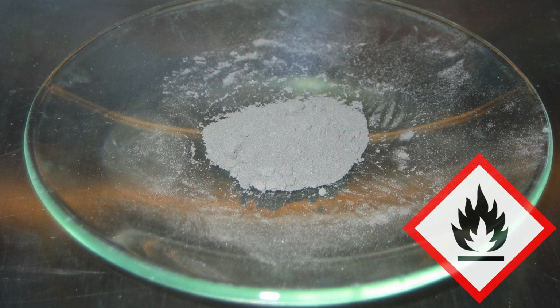Its structural and thermal stability, i.e. the fact that it does not decompose at high temperatures, allows its use under a wide range of reaction conditions. Additionally, the solubility of Raney nickel is negligible in most common laboratory solvents, with the exception of mineral acids such as hydrochloric acid, and its relatively high density, between 6 or 7 grams per centimeter cubed, also facilitates its separation off a liquid phase after a reaction is completed.